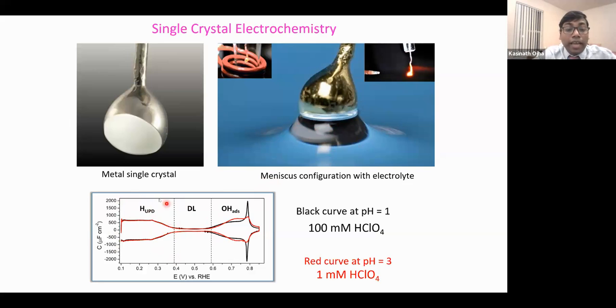This region we call hydrogen UPD, or the hydrogen adsorption region. If you scan this way, hydrogen is desorbing from the surface, and if you go this way, hydrogen is adsorbing on the surface. Then if you go more negative, you start hydrogen evolution reactions, and before that you deposit a lot of hydrogen on the surface. On the other hand, this high potential region is the OH adsorption region. Here you adsorb OH, while you scan back, you desorb OH.